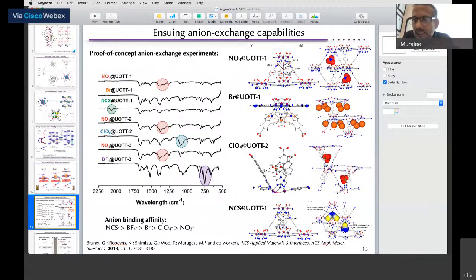So you can do an ion exchange, but not complete removal, because what we are trying to do is create different linkers that are redox active. That means we can avoid doing an anion exchange, and instead create frameworks based on radicals so that you can do redox activity with a more stable system. This one you have to always have an anion inside. If you have a redox active framework, you don't need to have an anion inside initially, and then you can put the anion in and remove it, and that's a system that we are working on currently.